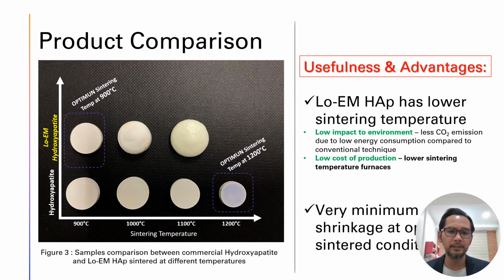Okay. So this is our initial study, where we compare the Lo-EM hydroxyapatite with the conventional hydroxyapatite. We tried to sinter hydroxyapatite at 900 degrees Celsius up to 1200 degrees Celsius. The optimum sintering temperature for the conventional method is above 1200. We can see that the shrinkage is a lot compared to the Lo-EM hydroxyapatite, where we have a great optimum sintering temperature with a good volume shrinkage percentage. And you can see that for Lo-EM, when we sinter above 1000 degrees Celsius, it starts to fuse. You can see the glassy phase already found on the surface of the product.